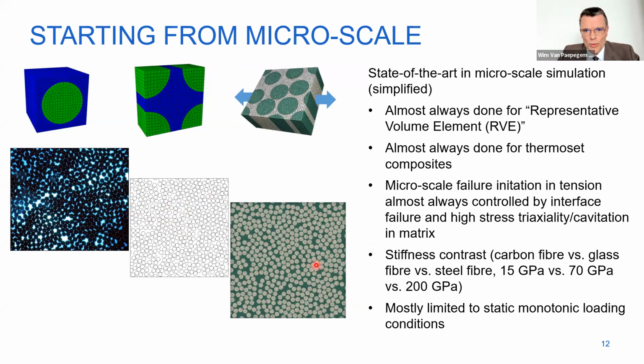I have to cut a bit corners in this short webinar, so a bit simplified, state of the art in the microscale simulation is typically done for these representative volume elements. Most of the time for thermoset composites, you don't find that many simulations for thermoplastic composites. And if you apply this transverse loading, what we will typically see first is interface failure and also a high stress triaxiality in the matrix.